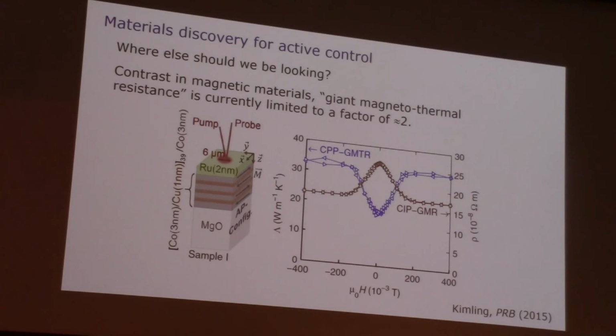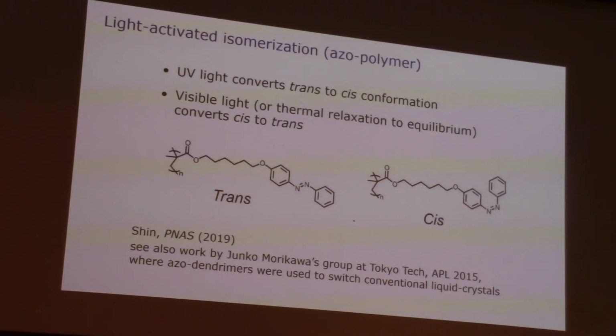magnetic moments become aligned. So this is the same as GMR, giant magnetoresistance, if you're familiar with that, but it's just the thermal analog of it. So the red curve is the GMR. This is the thermal GMR. This means transport perpendicular to the plane. And the thermal conductivity again changes by about a factor of 2 with the application of a magnetic field in this material. And like I said, this in principle is extremely fast. It's really whatever the speed is of that switching, and that switching is related to things like ferromagnetic resonance, and that's gigahertz. So sub-nanosecond kind of problems. Here's one from the soft matter world, right?